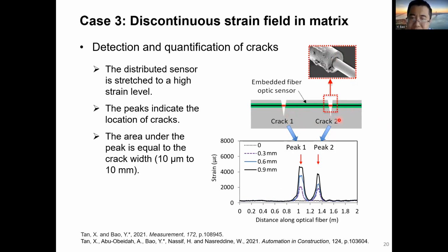So for example, here we have two cracks, crack 1 and crack 2. At each crack, the fiber optic cable was stretched to a higher strain level as shown by the red color. So because of this increase of tensile strain, we could detect peaks in the strain distribution along the length of the optical fiber. So the position of the peak in the measured strain distribution reflects the position of the crack in the structure. And also the magnitude of the peak is related to the crack opening width.